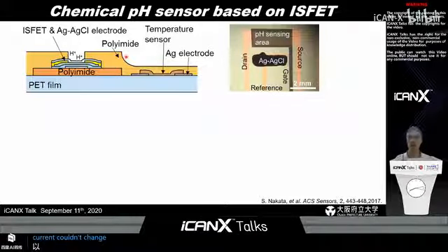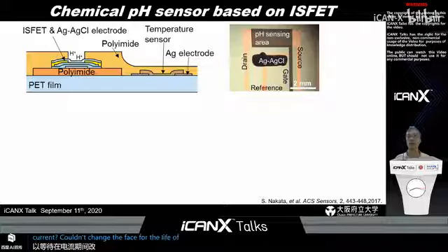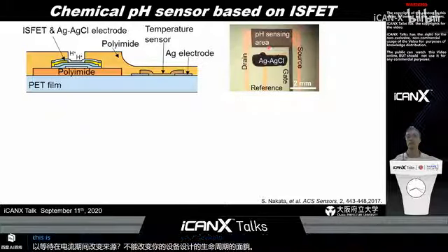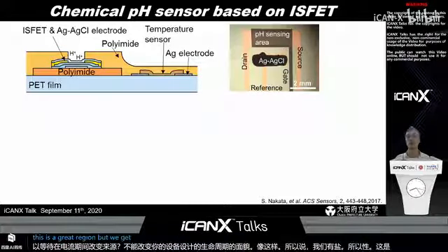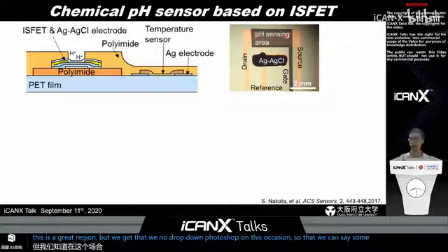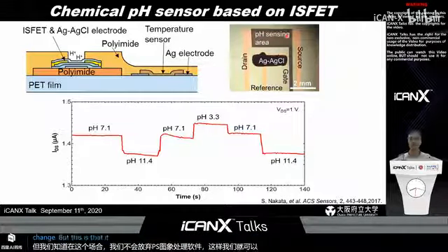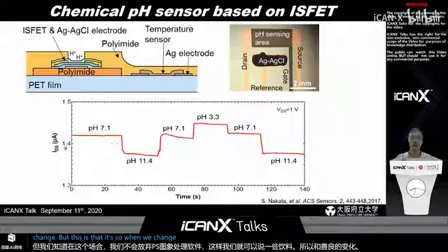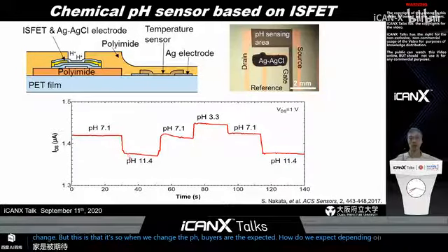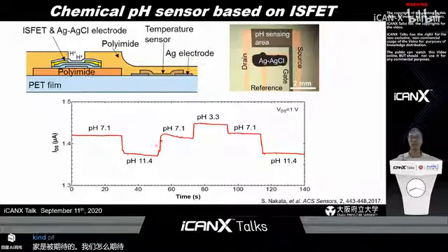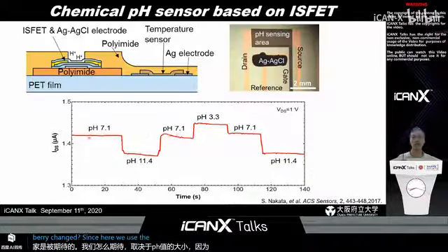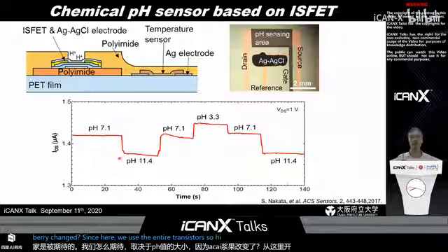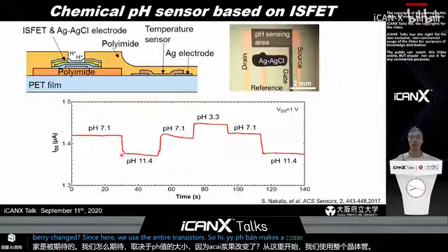That's why our device design is something like this. We have a source and drain electrode, and this is the gate region. We drop the solution over this gate region so that we can see the source drain current change. So this is the result. When we change the pH value, as we expect, the current level changes depending on the pH value. Since here we use N-type transistors, a higher pH value makes a lower drain source current.